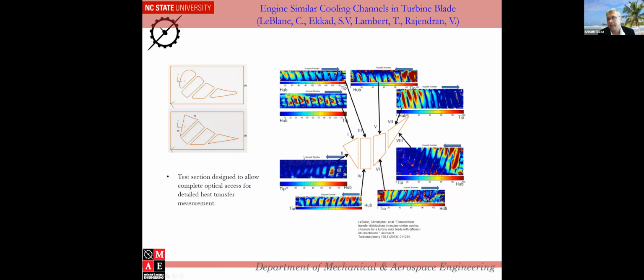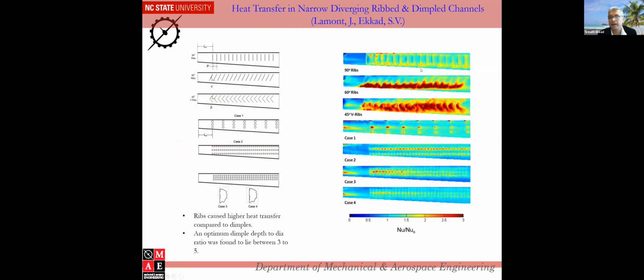And what you're going to see is how non-uniform the heat transfer coefficients are on the surface. On this channel, you see very low heat transfer on this surface, but on this surface, you see very significantly high heat transfer. This distance could be about 30 millimeters, and you are seeing a significant difference in heat transfer. Similarly, you can see this side and this side showing differential heat transfer. Again, this side is showing different. And then the last channel, again, you see there's absolutely no cooling at the tip of the blade as the flow goes up. So we presented this data, and that led to some more work from GE.